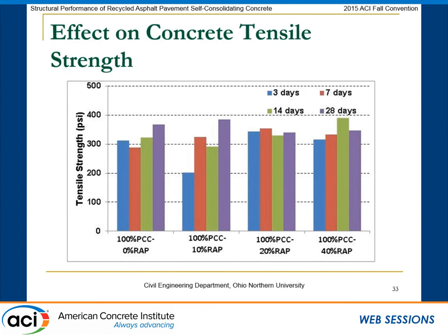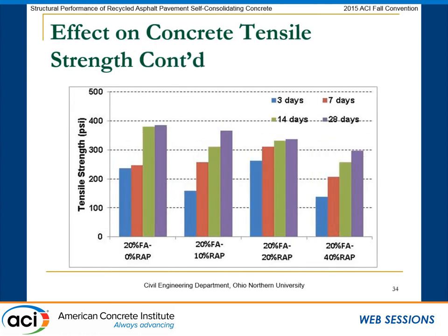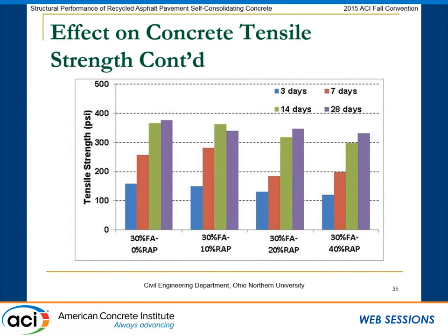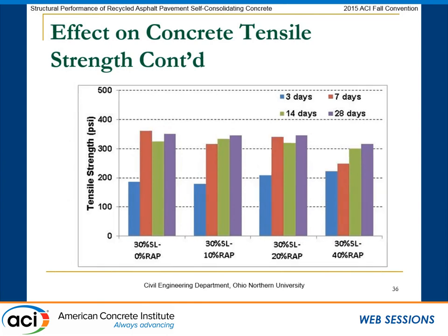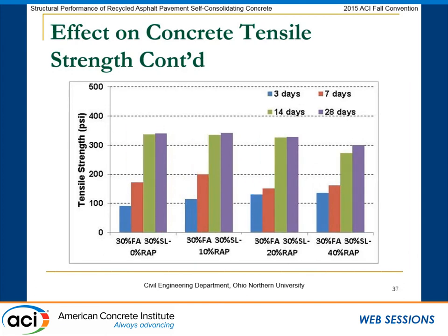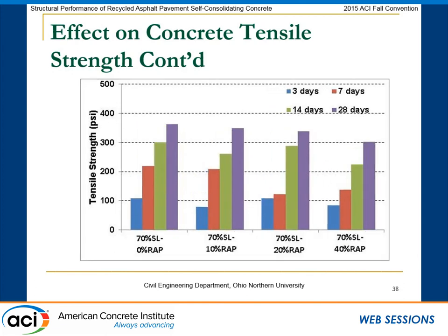or 28-day. Okay. If you look at the tensile concrete strength, they showed a similar trend to the compressive strength. Again, when 10% RAP was introduced, there was a slight increase, but then this slide shows the trend as the RAP content increases, your tensile strength also decreases. So maybe here it's a good idea to test adding fibers to these SCC mixes and see how this would improve the tensile strength capacity. For fly ash, you can see also the same trend, and for 30% slag, you can see the same trend,